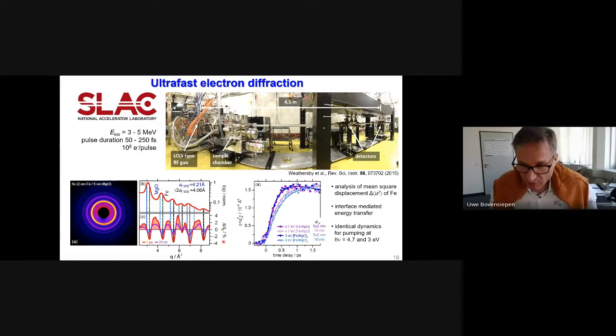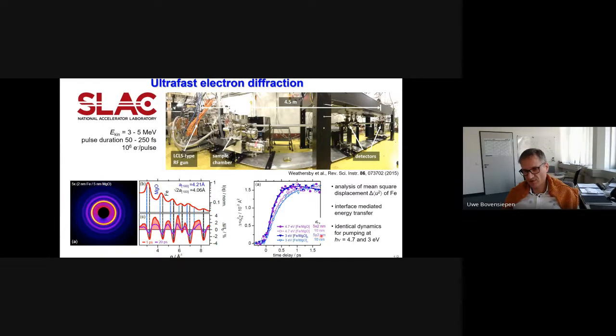Okay, so why do we do this experiment? With diffraction experiments, I mean, recall the Debye-Waller effect, for example, we analyze the mean square displacement, delta U squared, of iron upon laser excitation. And you see here this resulting mean square displacement change upon laser pumping as a function of time delay. And I show you here 4 data sets. First, let's look at those of the heterostructure. This is 5 times 2 nanometers in dark blue, and here this magenta. This gives the fastest response, yeah? And the data are right on top of each other.